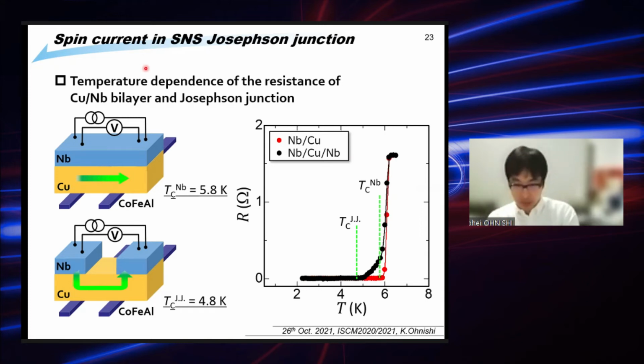Before the actual measurement, we first measured the temperature dependence of the resistance of the niobium copper bilayer and Josephson junction to confirm the transition temperature of the Josephson junction and the niobium layer. Without the junction, just the bilayer, the transition temperature is 5.8 Kelvin. This red line indicates that.